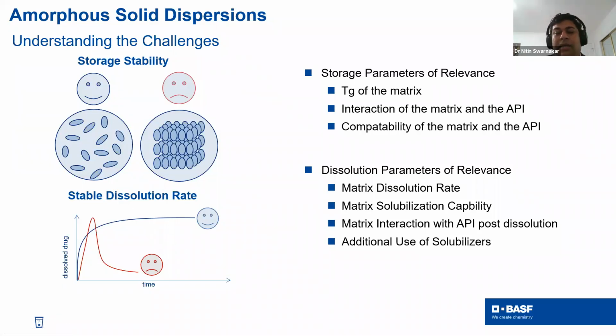Now coming on to one more part, which we're going to discuss later, but I want to point it out here: sometimes when you prepare extrudate from hot melt extrusion, the cooling rate is important too. If your cooling rate is faster or slower, that also changes the drug mobility in the matrix. If you get a hot melt extrudate which is really hot, and you take the time to cool it down, ultimately, because it is very hot, the polymer chain is more flexible, and API will get the chance to interact. So cooling rate is also one of the major issues which we generally see.